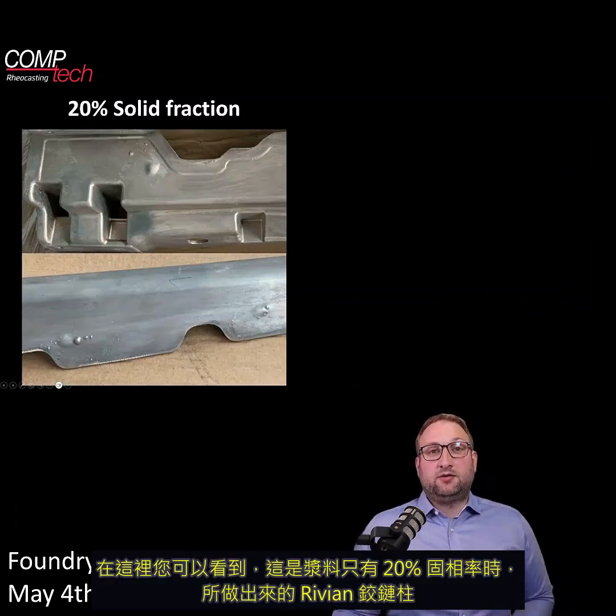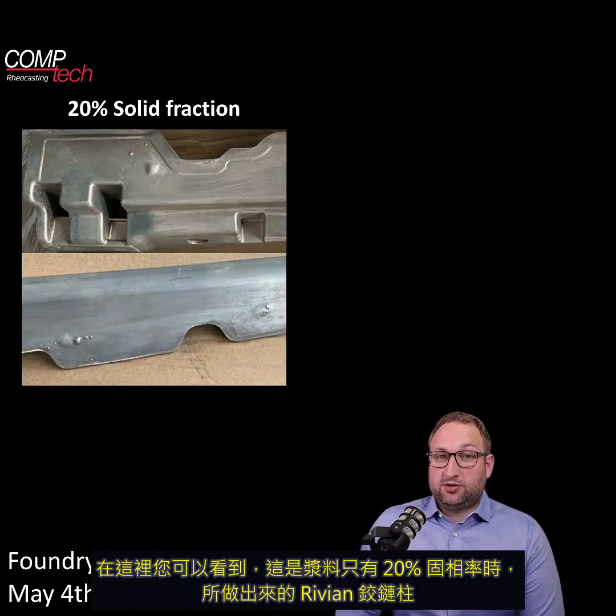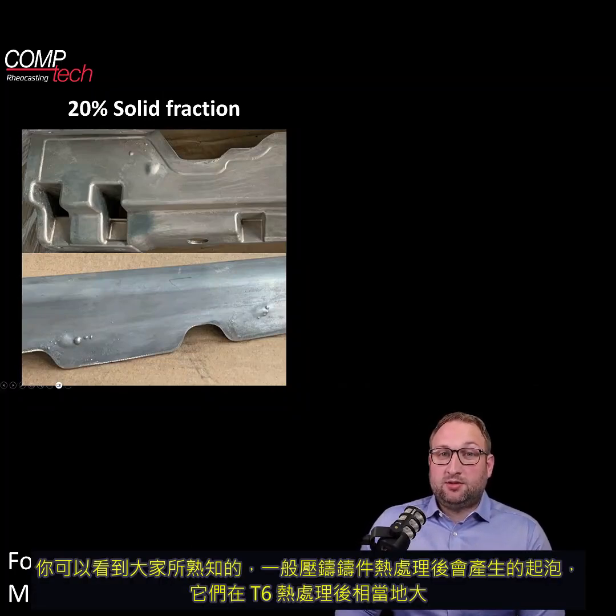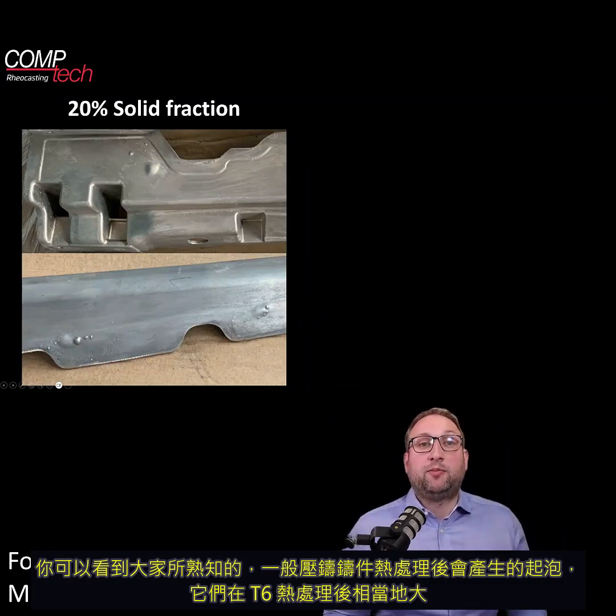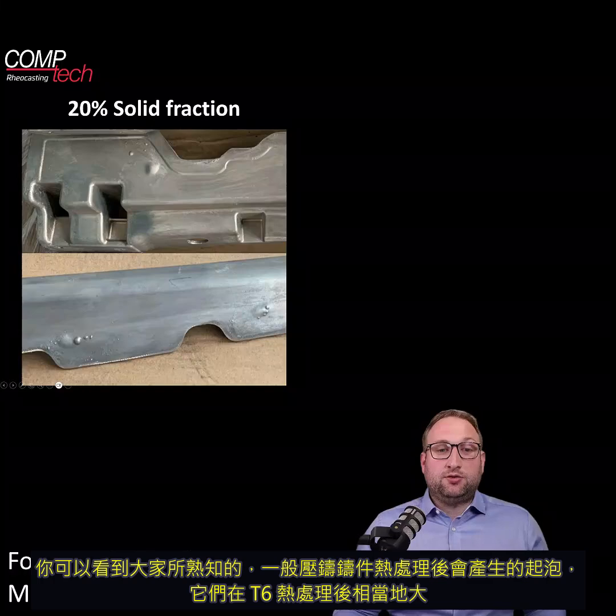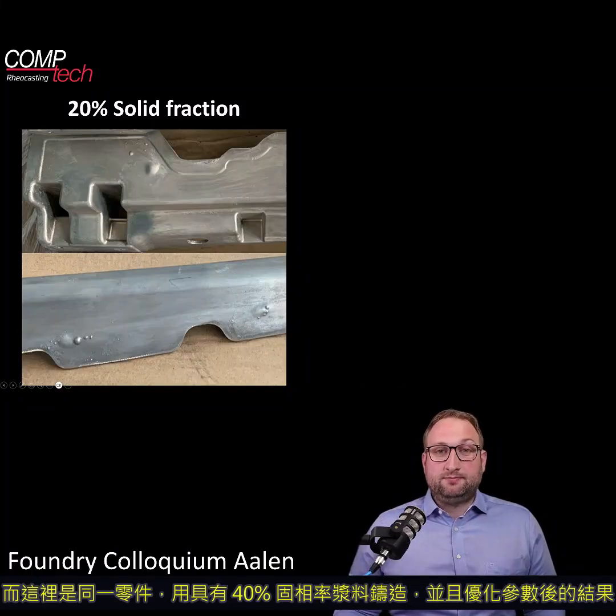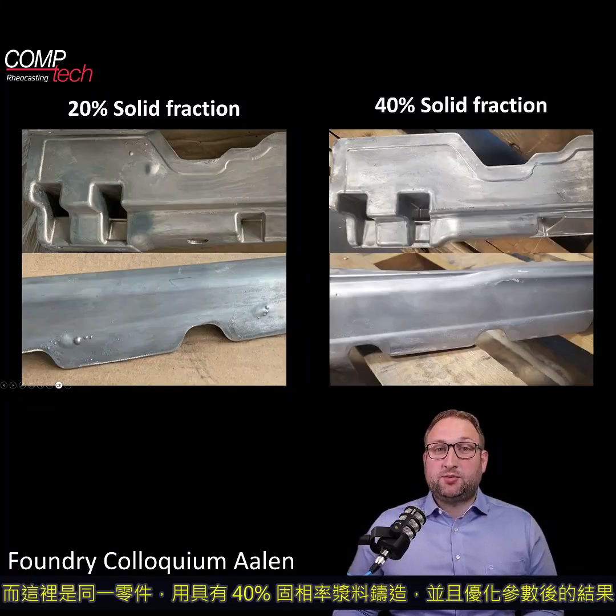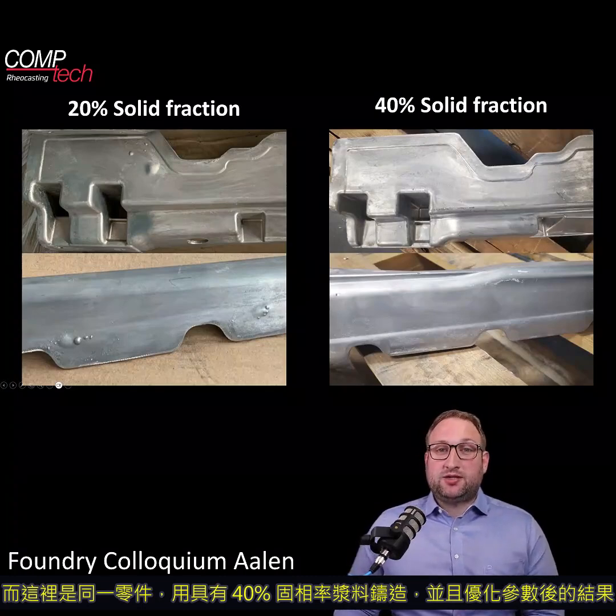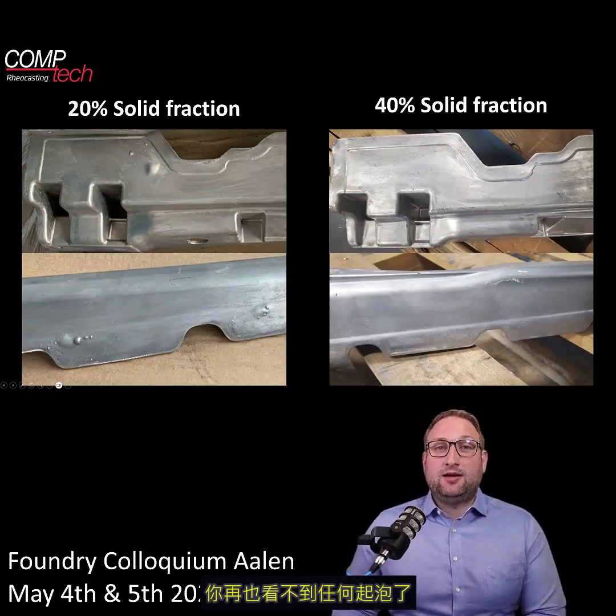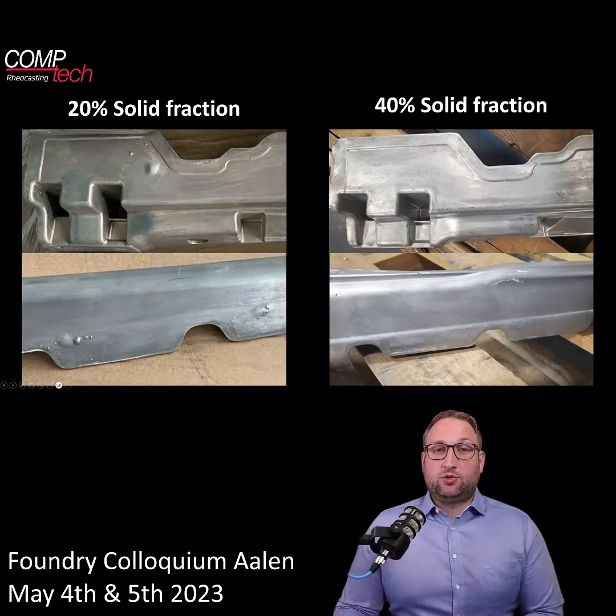Here you can see the Rivian hinge pillar with just 20% of solid fraction for the slurry. You can see the blisters like you know it from high pressure die casting, and they're quite huge after T6 heat treatment. The same part with the optimized parameters at 40% solid fraction: you cannot see any blisters anymore.